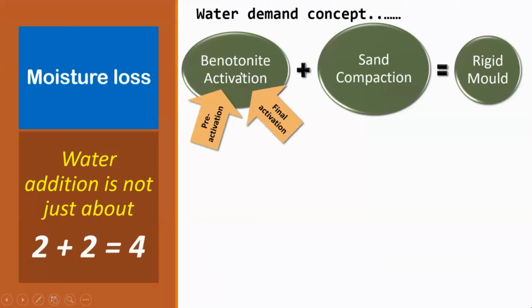So what is bentonite activation? It can be seen in two ways. One is pre-activation, the other one is final activation. And for compaction, there is what is called temper water. Now, what is pre-activation? Pre-activation is before the sand goes into a sand mixer. The sand should retain some water so that your bentonite, which is remaining inside the return sand, is activated to an extent and then reduces the load on the mixer.